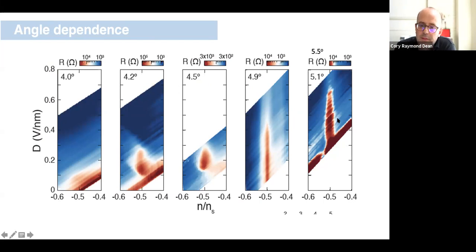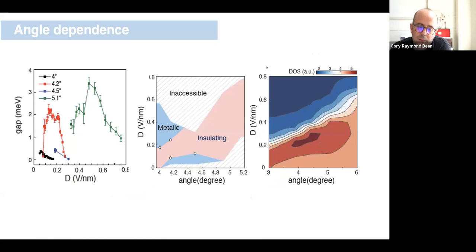Okay, so nonetheless, within this angle range that we can access, we see a fairly remarkable, to my mind, coherent evolution of the data. What we see is as we increase the twist angle, this half band insulator spans a well-defined displacement field for reasons that I just discussed. And the evolution of the boundaries of the displacement field seems to be evolving systematically with twist angle. So again, the question is, can we correspond that to single particle band structure? Because those calculations seem to do a fairly good job of explaining qualitatively the data we just described for the one device. And indeed, we can map out.